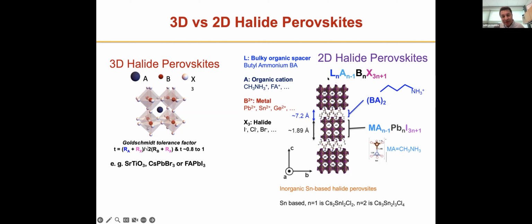And so what you have is the perovskite octahedra, which is this typical ABX3 type structure. And then separating these are these organic spacer layers. And so you end up getting this superlattice-like structure, which consists of the inorganic and the organic layer, which is continuous throughout.